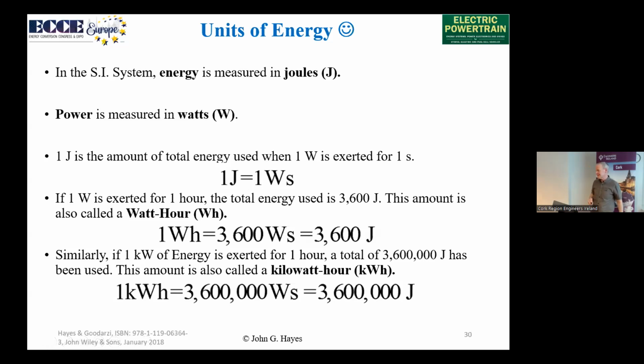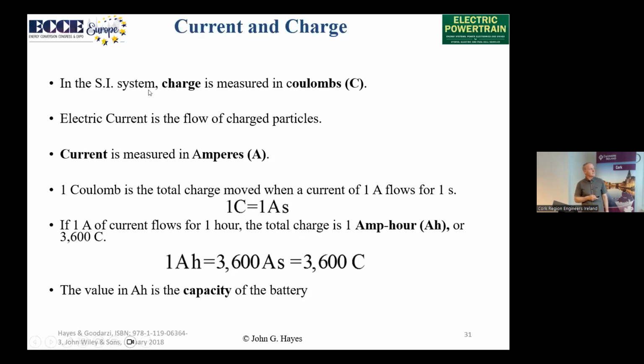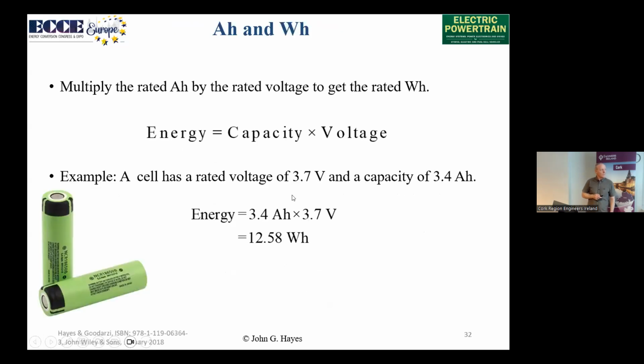Now we're going to put together the energy with the chemistry. In the SI system, charge is measured in coulombs, named for a Frenchman. Current is the flow of these charged particles, and that's named for Ampere, also a Frenchman. So 1 coulomb is 1 amp for 1 second. 1 amp hour, which is what we often use for batteries, is 1 amp for 3,600 seconds, and that's 3,600 coulombs. So amp hours is the term we use to describe the capacity of a battery. But certainly in car batteries, we tend to talk about watt hours. So we take that capacity, which is amp hours, and multiply it by voltage, which is volts, and that gives us watt hours, because volts times amps is watts.